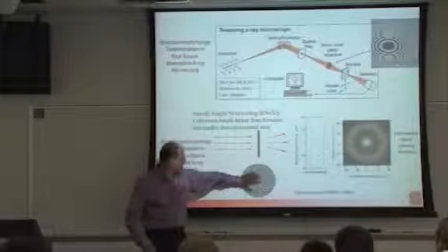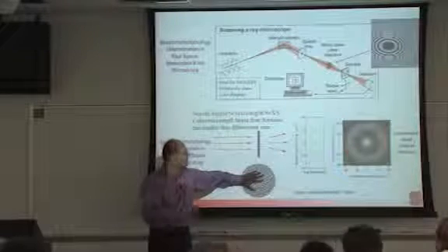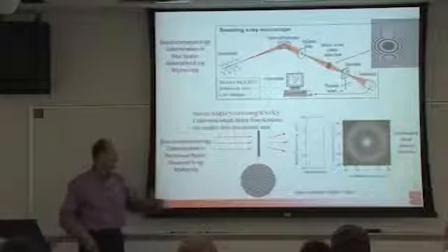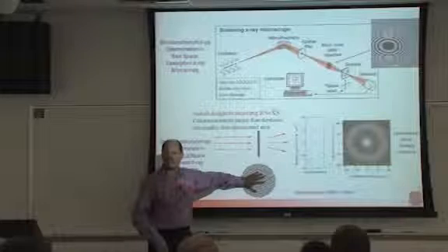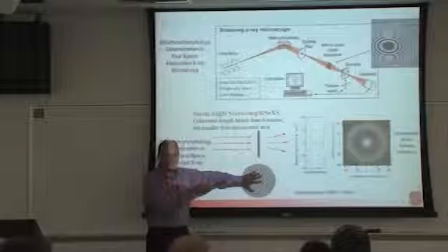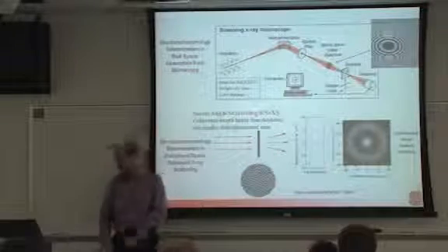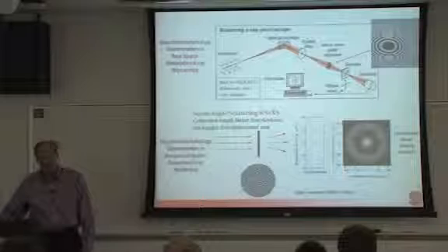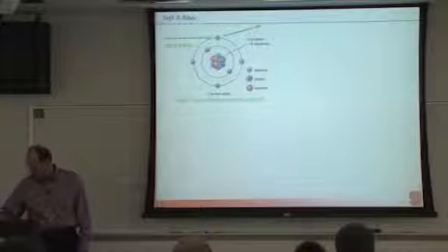And then, of course, if I change the gray levels here and I lose contrast, what would happen? The intensity of my scattering would go down. So using the scattering intensity gives me an idea of what the composition fluctuations are, and where I get that size scale here in reciprocal space tells me what the domain size or the domain size distribution is. So that's the one tool.